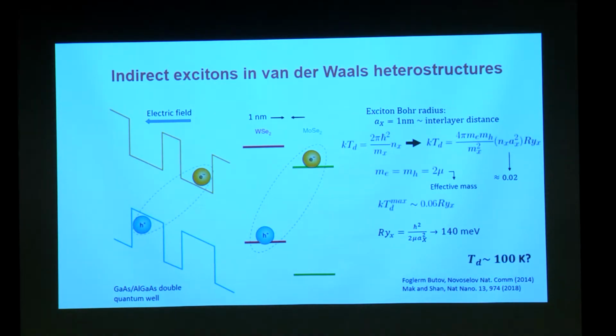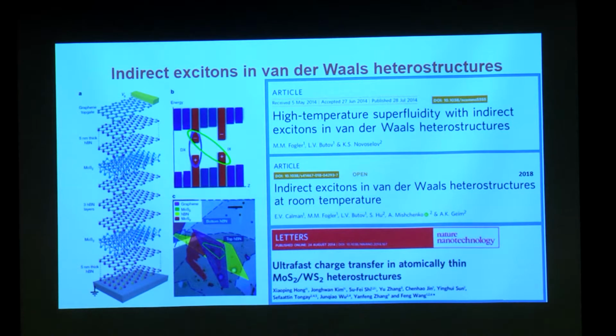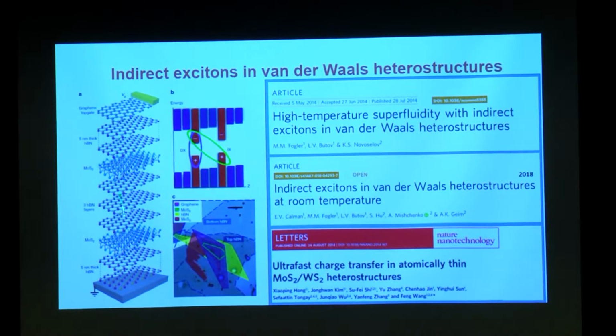Right. Now, this has been realized, not the condensation part, but the fact that it forms an indirect exciton. This has been done in several groups over the last 4 years, and we now have even van der Waals heterostructures of such complexity in which the two semiconductor layers are these two, whereas here the insulating layers can be individual boron nitride layers, and you can change the distance between them at will with today's van der Waals heterostructuring technologies. Okay? So this is a very potent and very versatile direction of research that's going on.